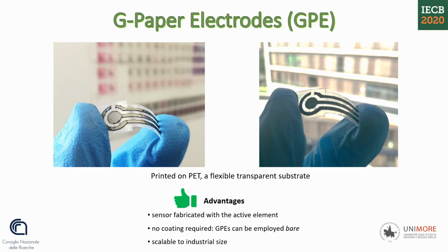In these pictures you can see G-paper electrodes. These electrodes are ready to be employed, they are built directly with the active element, which is graphene, and they are printed on PET, which is a flexible transparent support. These electrodes were first tested for their electrochemical conductivity with a benchmark redox species, which is ferrocene dimethanol.